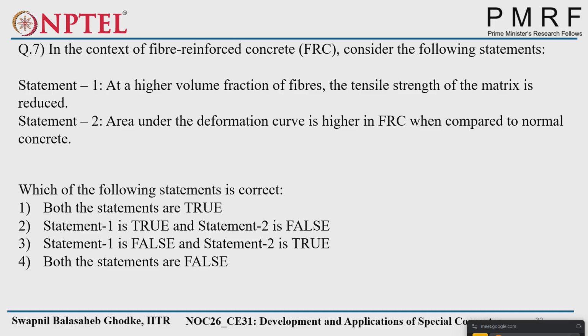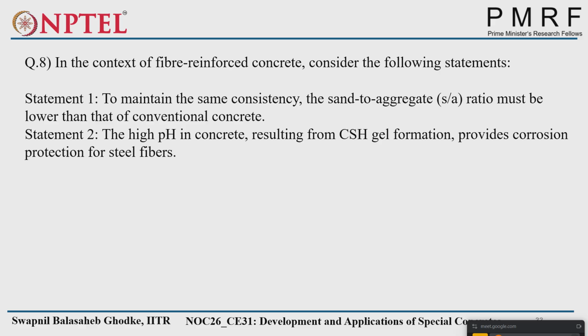Next, in the context of fiber reinforced concrete. Statement 1: at higher volume fraction of fibers, the tensile strength of the matrix is reduced. Statement 2: area under the deformation curve is higher in FRC when compared to normal concrete. What will be the answer? First false and second true. Correct, because tensile strength of the matrix improves, it does not reduce. And area under the deformation curve is higher in FRC compared to normal concrete is correct. Statement 1 is false and 2 is true.